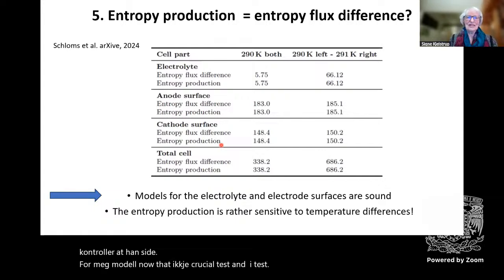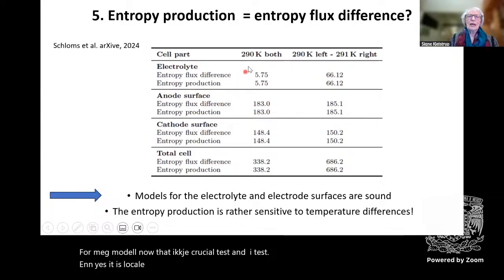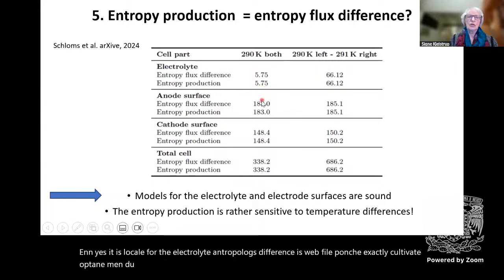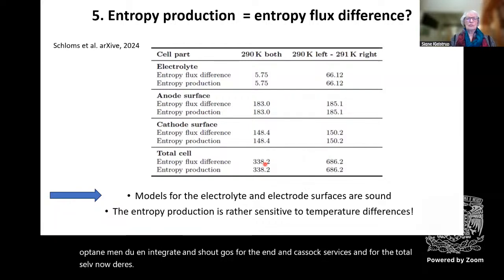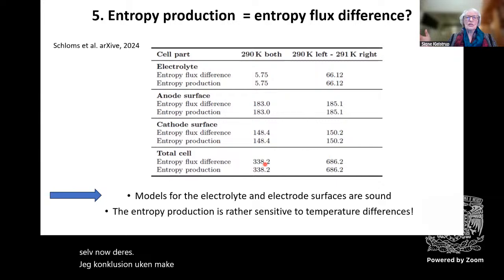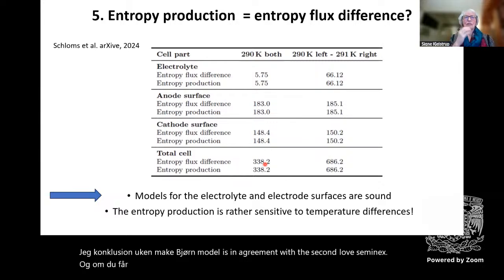And yes, it is. Look here for the electrolyte, the entropy flux difference is 5.75, exactly equal to what you obtain when you integrate. And so it goes for the anode and cathode surface and for the total cell. And now there is a conclusion you can make. Your model is in agreement with the second law of thermodynamics. Wonderful conclusion, I think. We can use this equation to sort out what is thermodynamically sound and not.